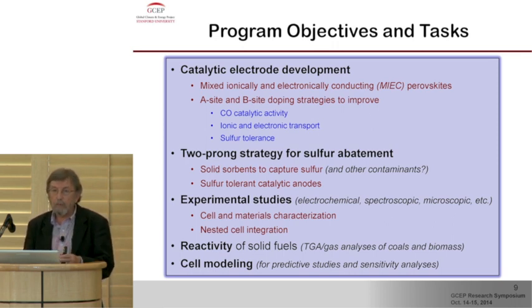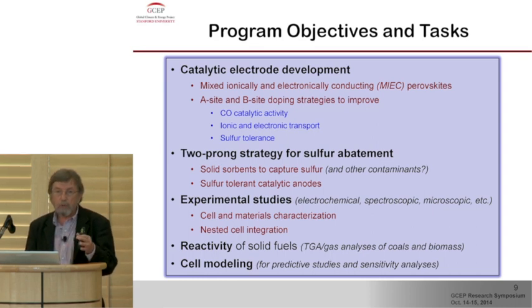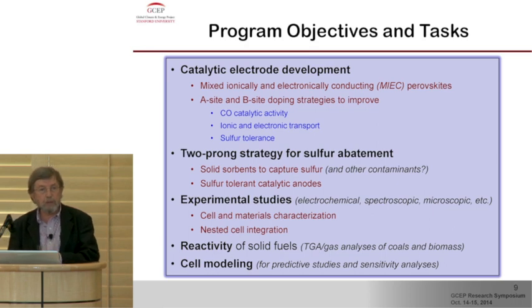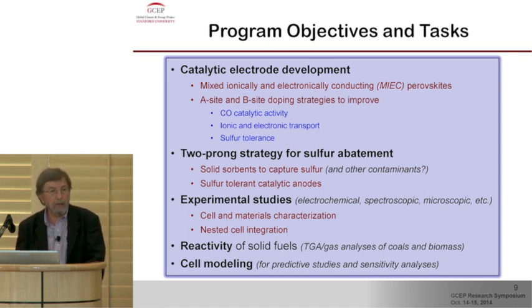We try to develop solid sorbents to bring down the sulfur activity to acceptable levels where the anode is going to operate without too much degradation. And of course, at the same time, we'd like to develop tolerant anodes that would take that level of sulfur and be able to do the job without degradation. So the electrode development is going to be an important portion of this project. Normally, nickel cermet and other metal anodes are used in solid oxide fuel cells, but they are not, of course, acceptable in the presence of sulfur.